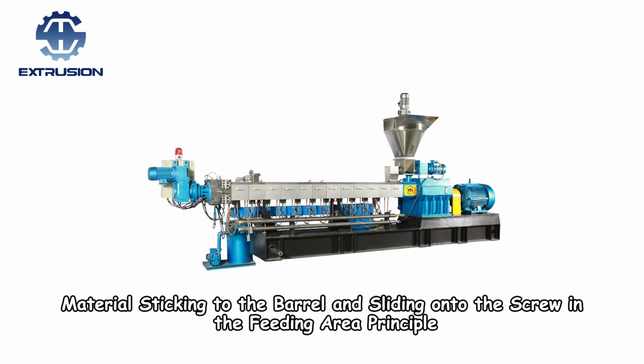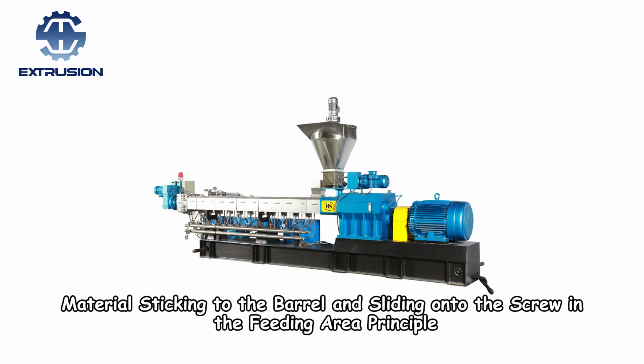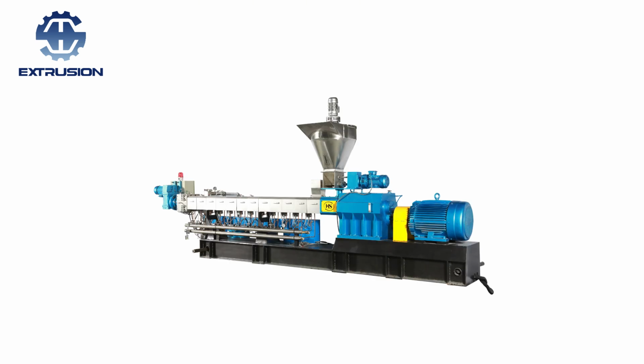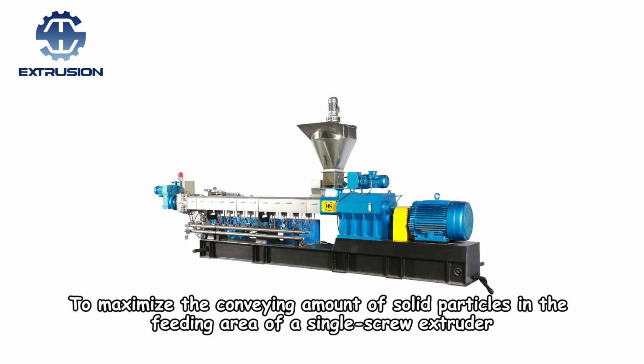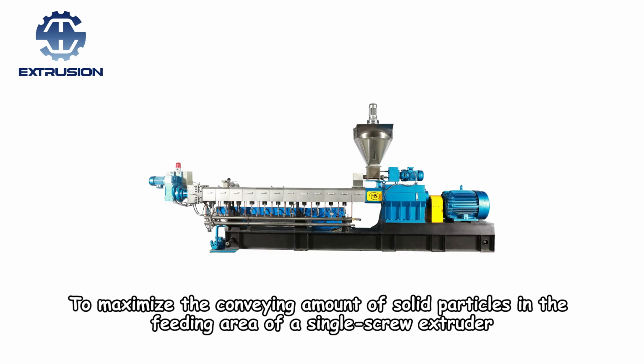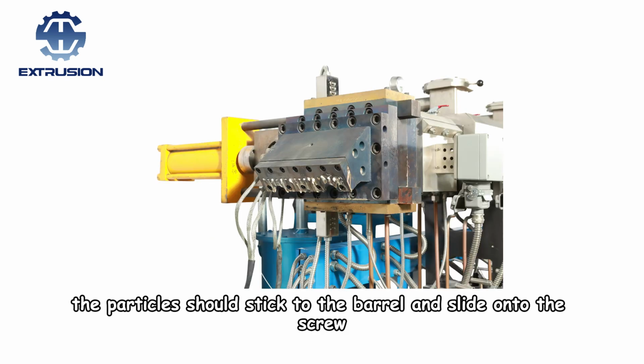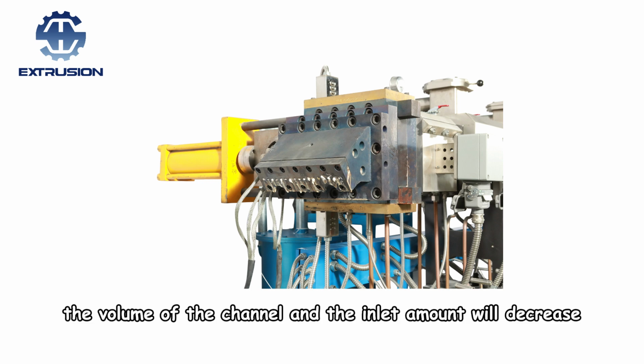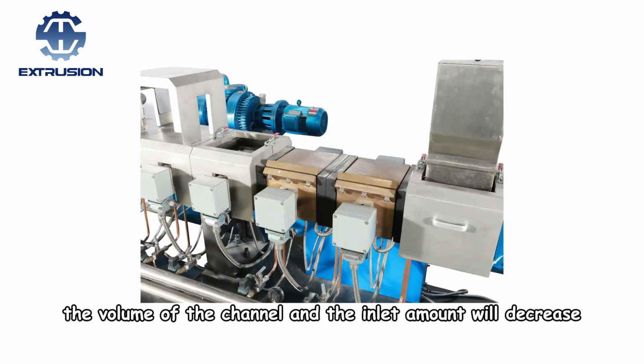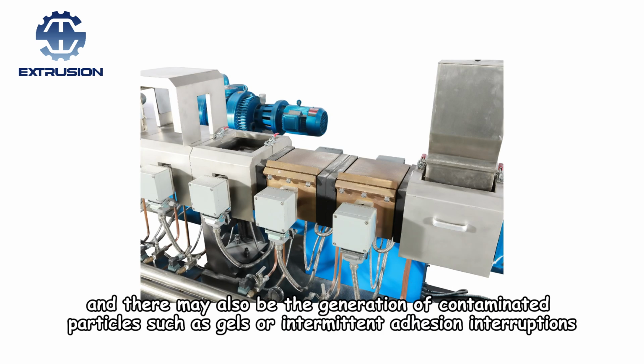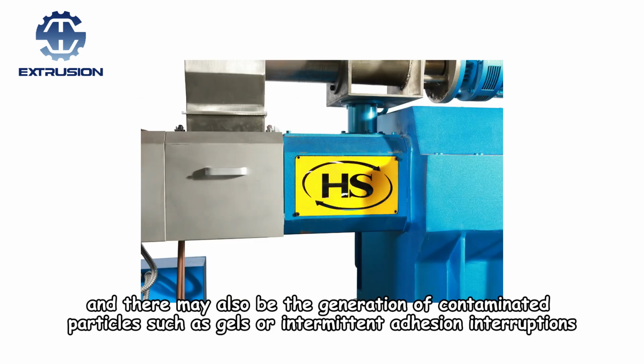5. Material sticking to the barrel and sliding onto the screw in the feeding area principle. To maximize the conveying amount of solid particles in the feeding area of a single screw extruder, the particles should stick to the barrel and slide onto the screw. Otherwise, the volume of the channel and the inlet amount will decrease, and there may also be the generation of contaminated particles such as gels or intermittent adhesion interruptions.